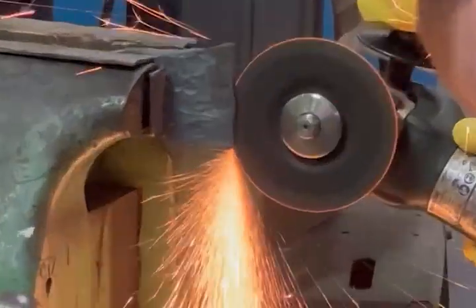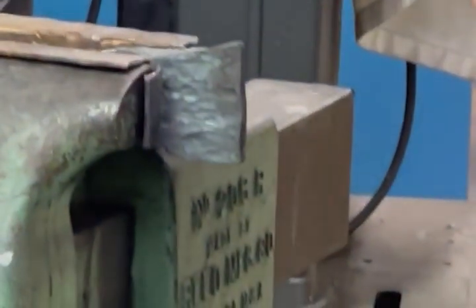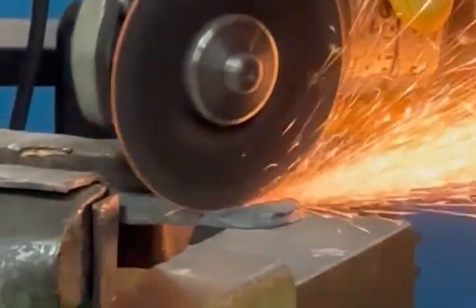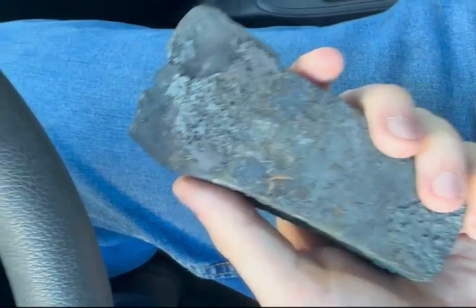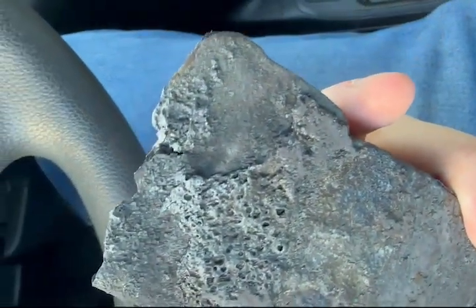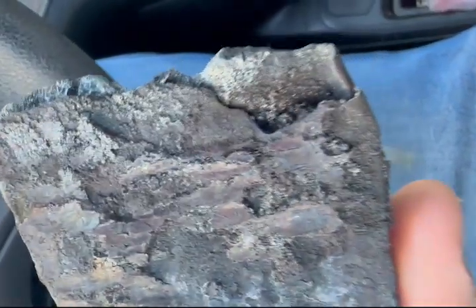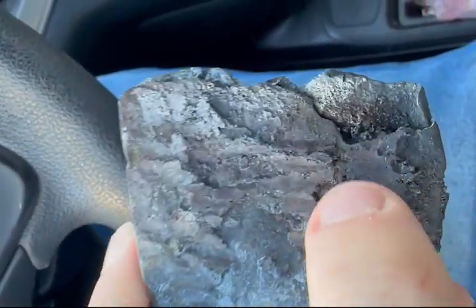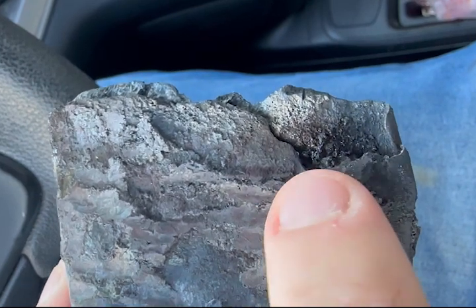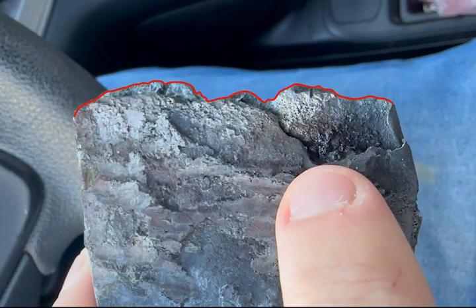After visiting the Office of Research's instrument repair shop and having a cut made on the narrowed end of the head as well as on the bit to prepare for forge welding, disaster struck. The footage of the forge weld attempt was unfortunately lost, but the footage of the aftermath is right here. We had neglected to consider the wildly varying structures between 4340 and 8620. As a result, forge welding wasn't just difficult, but nearly impossible at the skill level we entered this project with. This left the material jagged, cracked, and at one point entirely absent, where splitting the crack blew out part of the wedge, and ultimately not even welded together.